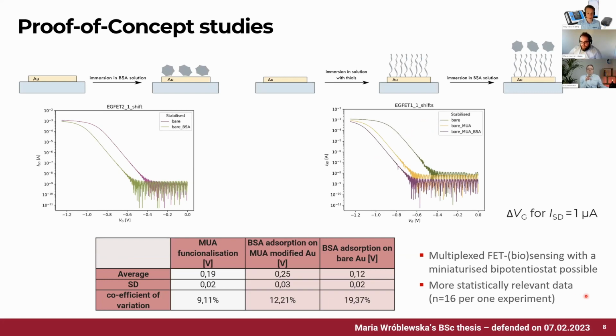Yeah, just maybe to point out here, we do not have increased noise. It's a constant amount of noise, but this is a logarithmic scale. So the same absolute amount of noise looks a lot bigger on a logarithmic scale in the area where the current gets a lot smaller. So don't forget, this current is going through multiple magnitudes. Yes, that's correct. And then you can see it's about 10 to the minus 8 amps, so this is 10 nanoamps current here. For such a very cheap and mobile device as the EmStat Pico, I believe this is still viable and feasible for measurements.